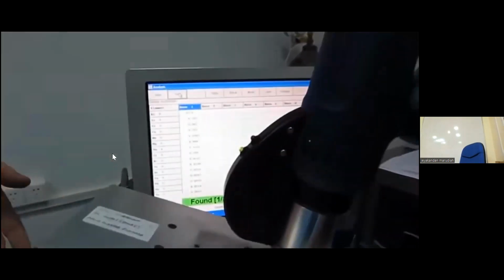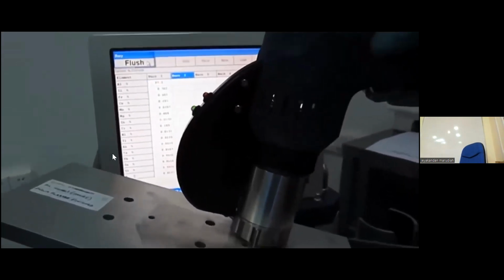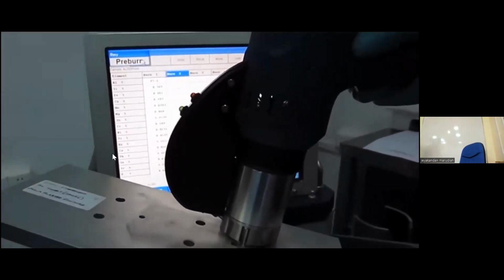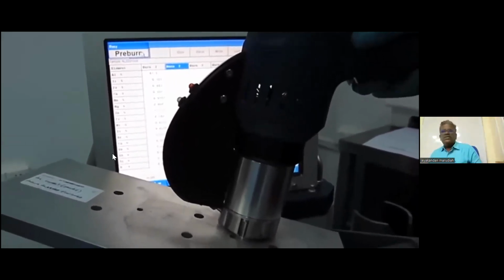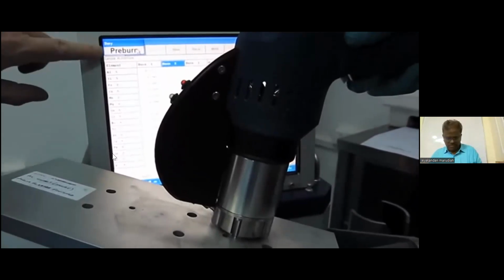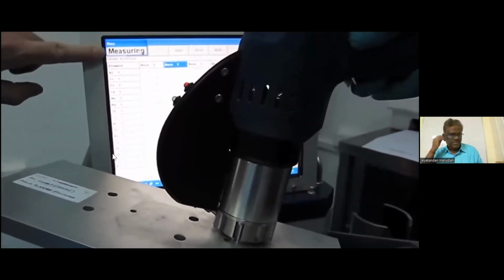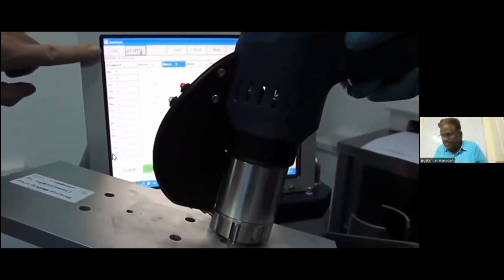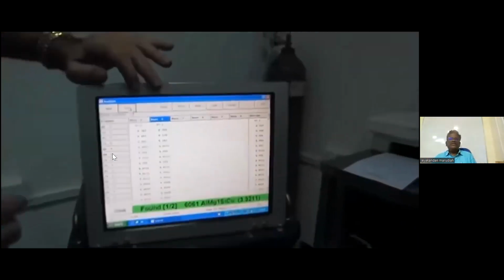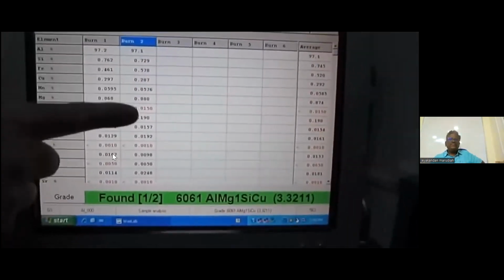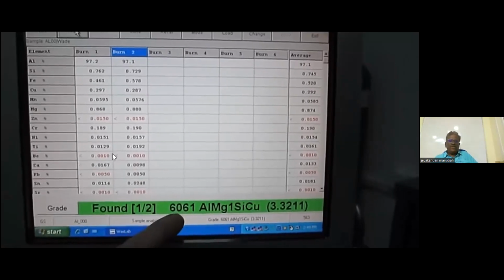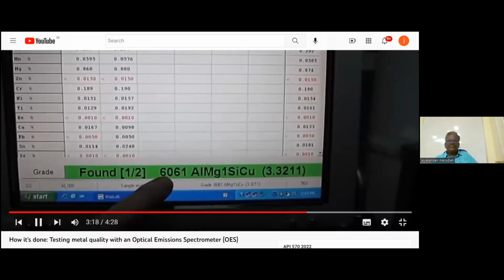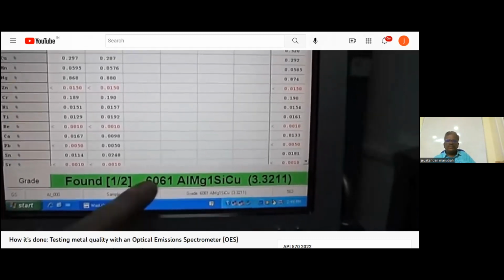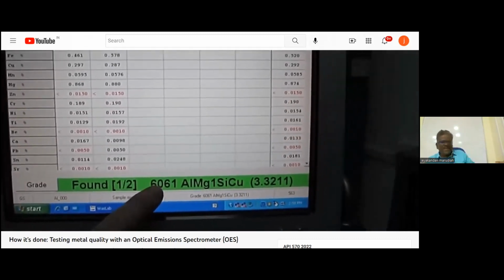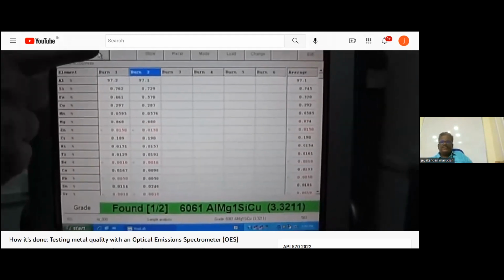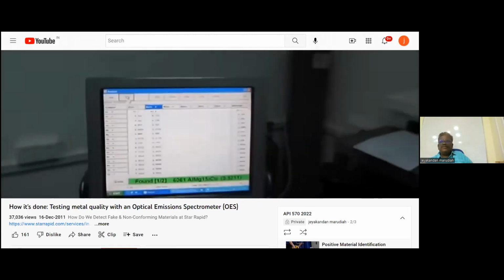So this is yet another sample of 6061 supplied to us. Now we're going to do a test on it. That was the second of 2 tests, and you can see the results here. The machine has automatically compared the results to its database and determined that the material is indeed within specification for 6061. So now I'm going to print off that report, and whilst that's printing,